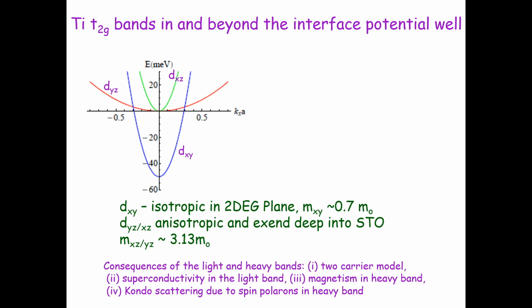And if I look at the electronic structure of the interface, these are titanium t2g bands, dxy, which is isotropic in the xy plane, and dyz and dzx. I have not put in any spin orbit interaction here. This is essentially because of the confinement along the z-axis and also slight distortion from the cubic symmetry. So that's why you are getting this splitting of these three bands. And so these are the effective masses band theorists have worked out. This is isotropic, and the band mass is something like this. And these are extended. They extend deep into strontium titanate, yz and zx. And the band mass here is higher, about 3.13 mass of electron.